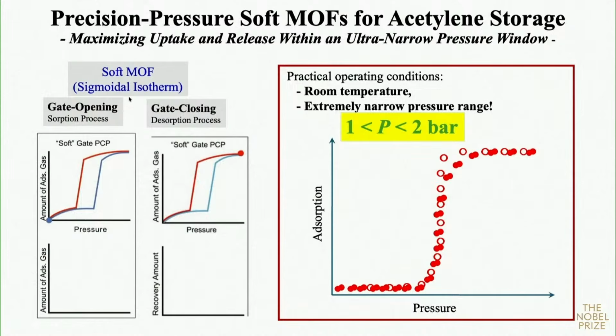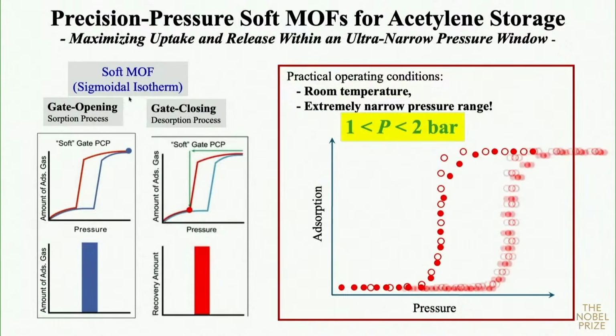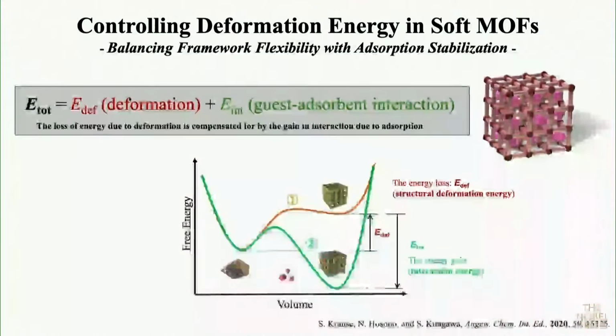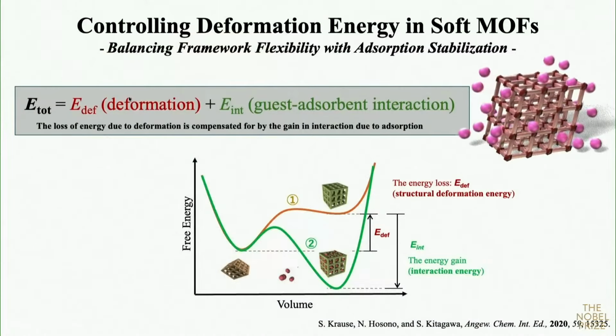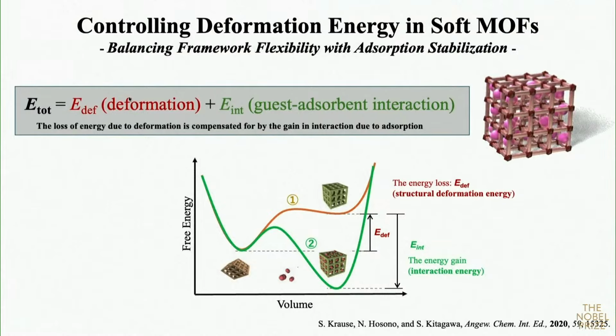But for a usable material, we need to control the gate pressure. So the sorption is like this, but we have to use acetylene again. So we need to control the gate closing pressure. What is difficult is that the pressure range is very narrow, larger than 1, lower than 2 bar. How can we control this? So our strategy is to accommodate the gas molecule. The structure should change to accommodate the gas molecule. So the deformation energy control is very important.